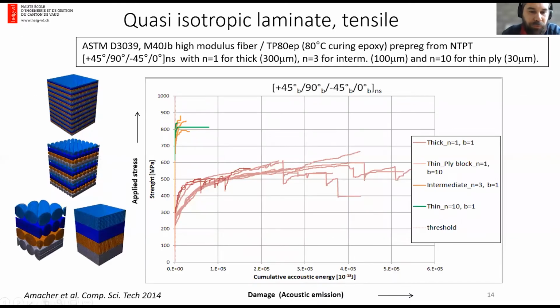And we can also observe this through acoustic emission monitoring. If we use acoustic emission probes and monitor on the horizontal axis the acoustic energy that is emitted by the composite, and on the vertical axis the stress applied on the composite, we can observe that for thick ply laminates, quasi-isotropic, the onset of acoustic emission is about 300 megapascal applied stress, and acoustic emission raises very quickly at around 500 megapascal and stabilizes here. This corresponds to the propagation of delamination, and the first onset corresponds to the nucleation of transverse cracks.